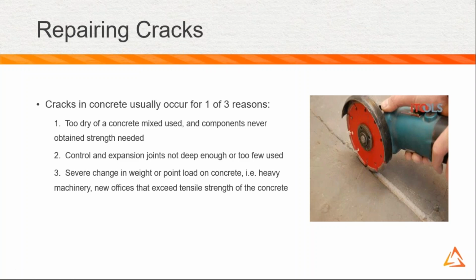Cracks in concrete usually occur for one of three reasons. One, too dry of a concrete mix used and components never obtain the strength needed. And that can happen for a myriad of reasons. As we get toward warmer weather, hopefully sooner than later, it's not uncommon for batch concrete trucks to leave the factory with a specific cement-water ratio, and by the time they get to a job site, it dries out a little bit. So that can be too dry of a concrete mix used.